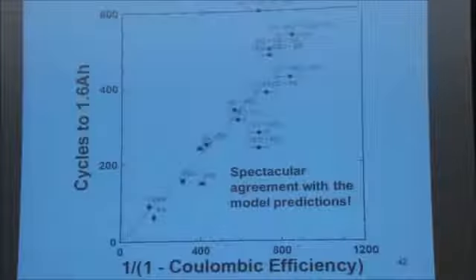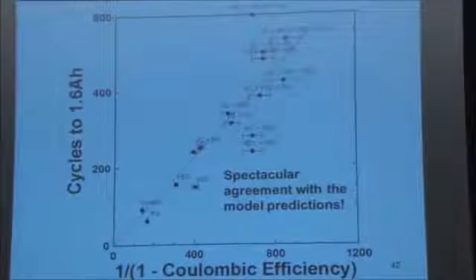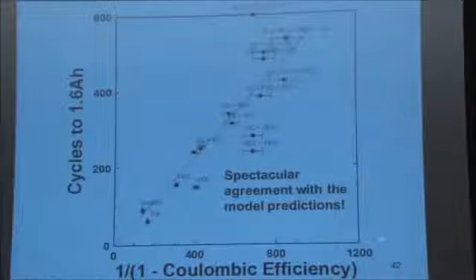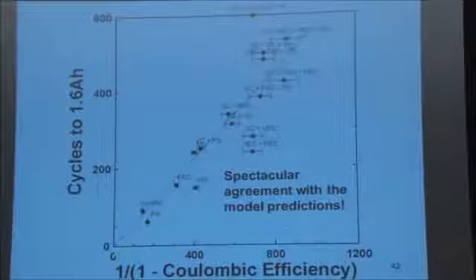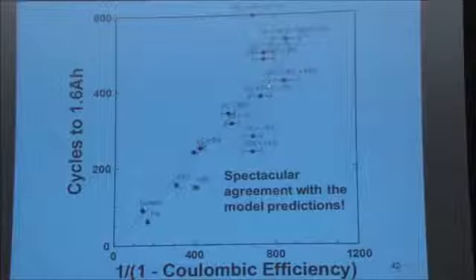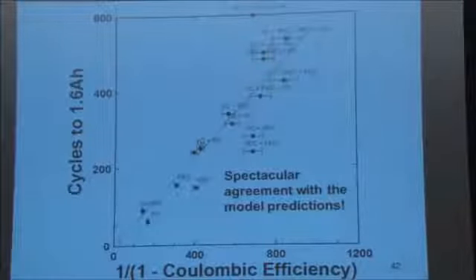So we did this. So here's the cycles to 1.6 amp hours versus 1 over 1 minus the Coulombic efficiency. And there's a pretty decent straight line agreement here for the electrolyte additives that we know what they are. It looks pretty good. There's some of them off the line, but really there's only 2 sets or 3 sets that are significantly off the line. It's pretty amazing. Nobody's ever done this kind of thing ever before.